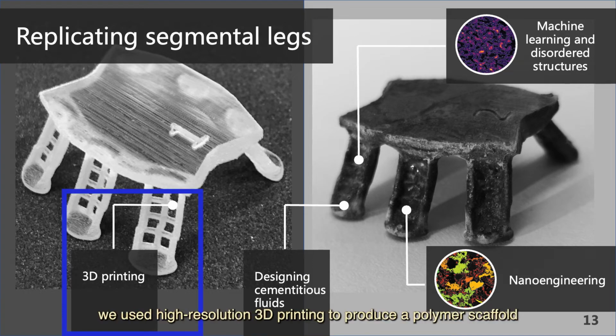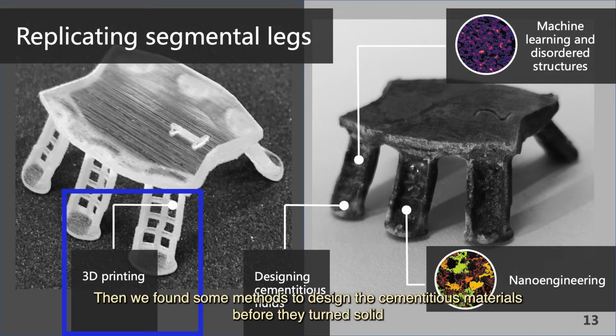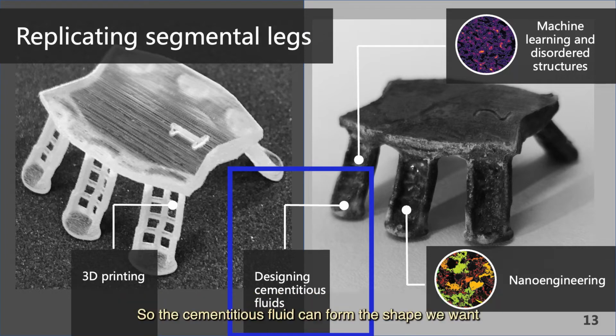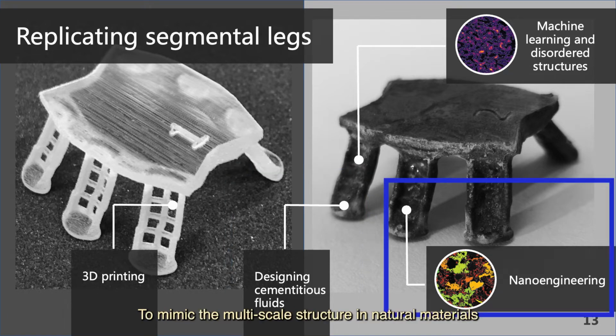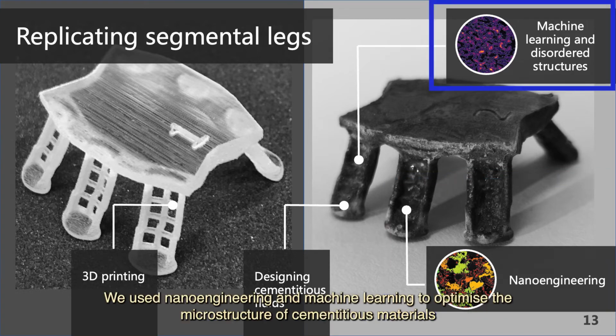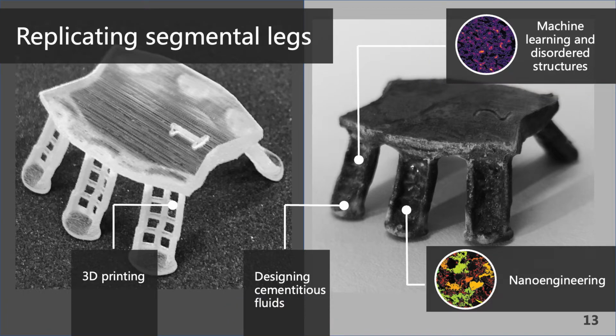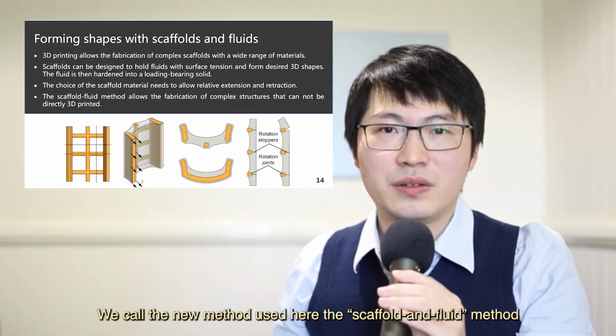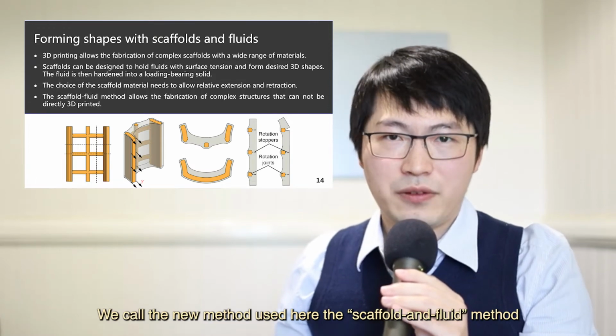First, we used high-resolution 3D printing to produce a polymer scaffold. Then we found some method to design the cementitious material before they turn solid, so the cementitious fluid can form the shape we want. To mimic the multi-scale structure in natural materials, we used nanoengineering and machine learning to optimize the microstructure of cementitious materials. We call the new method used here the scaffold and fluid method.